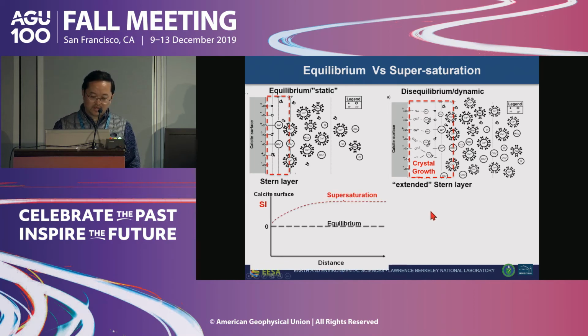So in terms of the saturation index of the system, you're looking at the mineral interface and going away from the interface, and this is a nanometer scale. You can actually see under equilibrium condition, the saturation index is pretty much 0, but under supersaturation, you have this profile that is related to the precipitation process of the calcite.